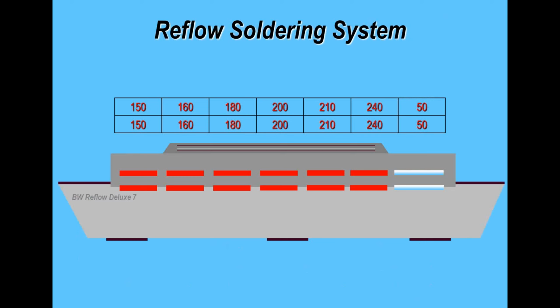So if we just look at an example, because obviously we're talking about the theory of the process today, not specific machines. So here we've got a Bob Willis Reflow Deluxe 7-zone machine, and I show the set point temperatures. Now one of the things to bear in mind, and a lot of engineers don't try this little trick, which is sometimes useful. What I'm showing you here is the set points all the way through the oven, and this is typical of what you will see in a user manual for a machine. And you can see that both the top and the bottom are mirror imaged. So you've got the top side and the bottom side temperatures the same all the way through the process.